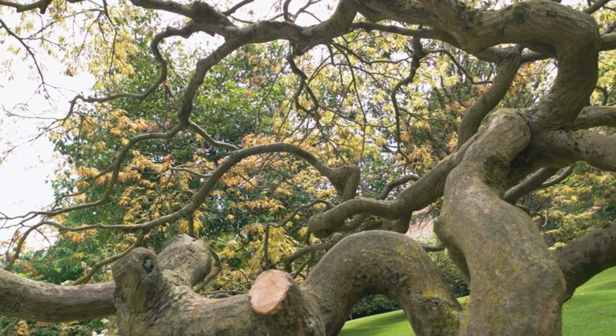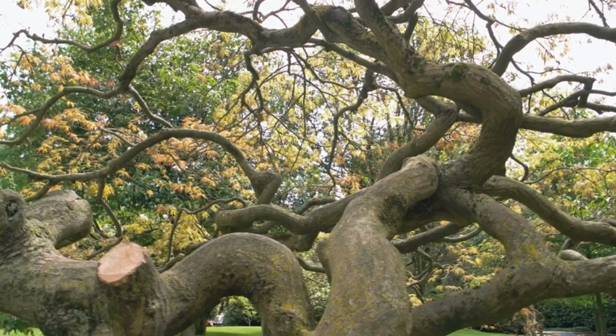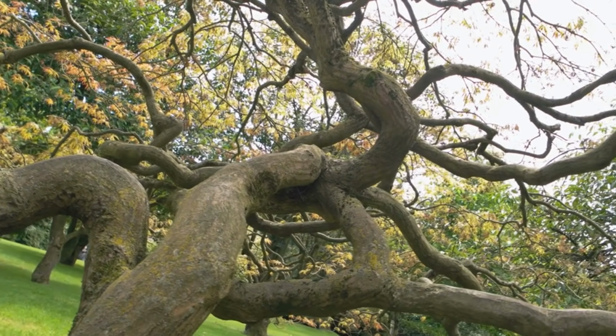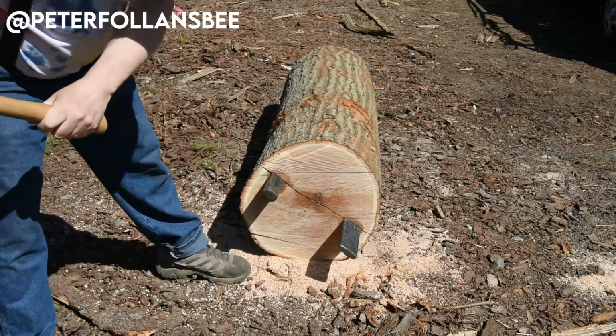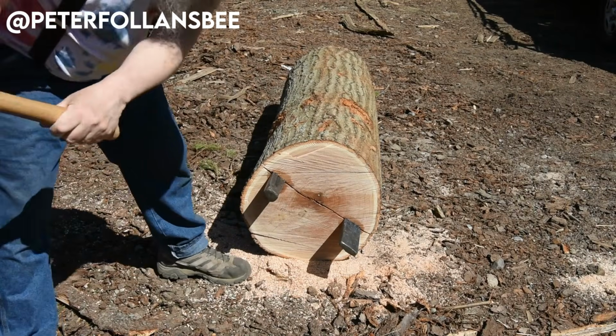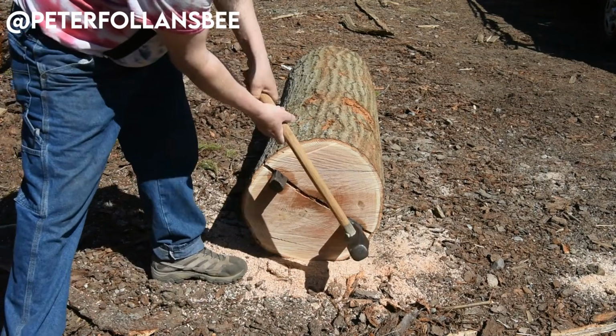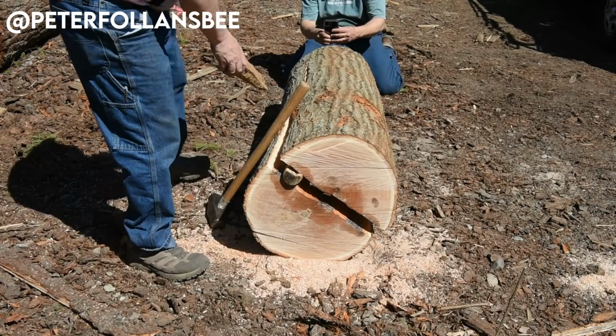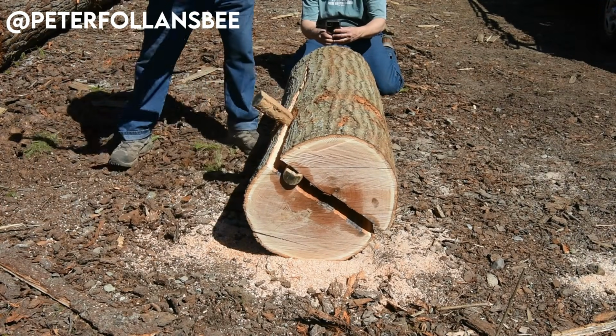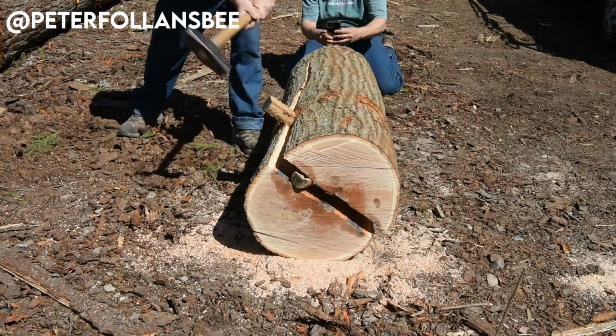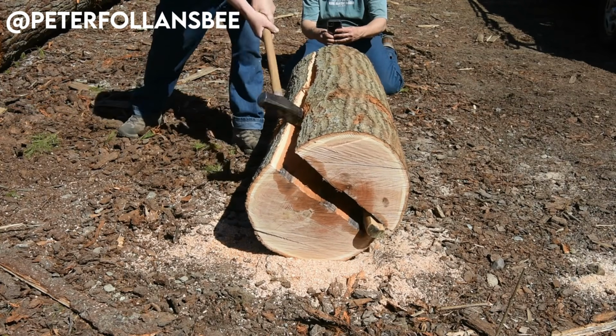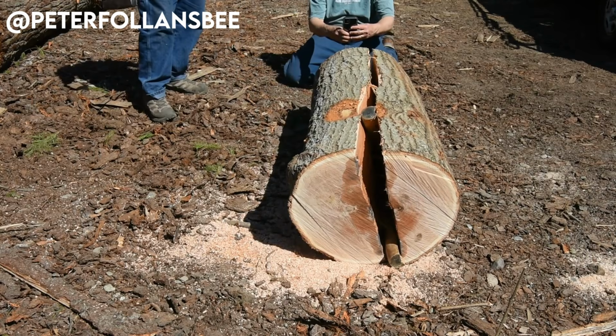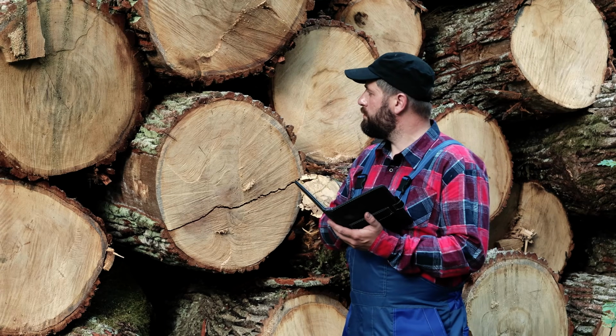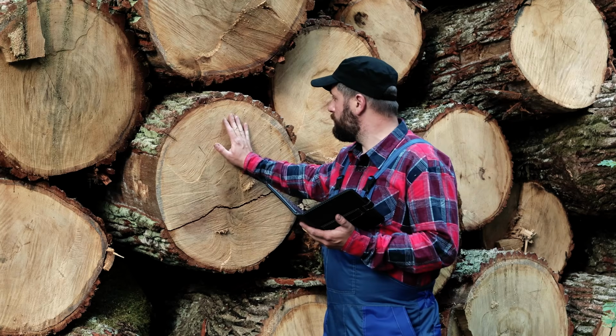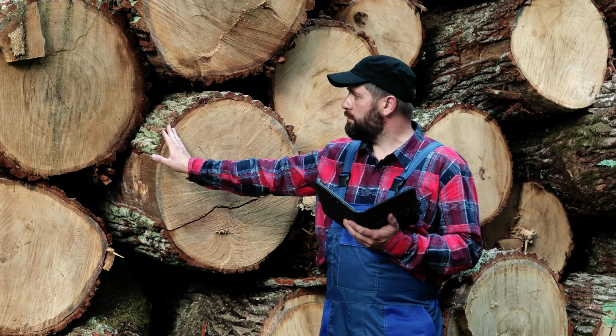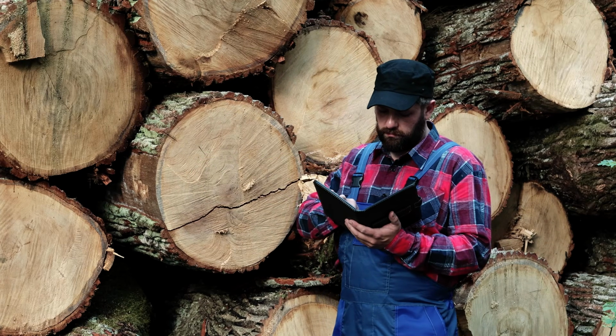Live oak is a southern species, Quercus virginiana, that grows in these sprawling, twisting forms along the coastal regions from Virginia down through Texas. The wood is extraordinarily dense, somewhere around 62 to 65 pounds per cubic foot when dry. To put that in perspective, white oak runs about 47 pounds per cubic foot. Live oak is nearly 40% heavier. But density alone doesn't explain why it survives saltwater. Live oak has an interlocking grain structure that makes it extremely resistant to splitting, and its heartwood is saturated with natural resins and extractives that are toxic to the fungi that cause rot.